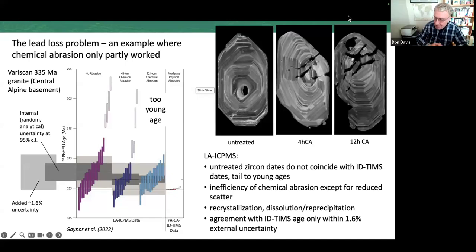Yeah, annealing doesn't actually restore the order of the crystal, except at a micro scale. If you have a zircon which is very low uranium, it's extremely hard to dissolve. If you put it, obviously, in your leach, it would still be there. If it's high uranium and you anneal it, it will still dissolve, but more slowly than it would in the disordered state. And it still dissolves because in the original crystal, you have one crystal, one coherent structure, whereas when you anneal it, you're producing a lot of microcrystals. You're basically recrystallizing the grain, but not uniformly, so that you still have a lot of surface area in between the crystallites where it can be attacked.